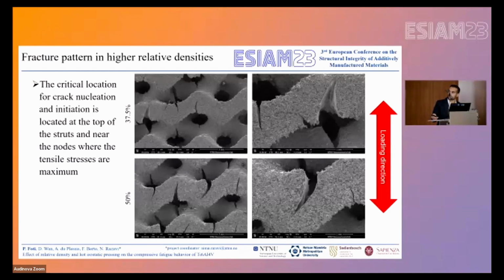If we go through the pre-failure analysis that we have carried out, you can notice that the critical location for the crack nucleation is at the top of the struts and near the nodes, and the cracks are perpendicular to the loading direction, in the struts that are experiencing a tensile stress.